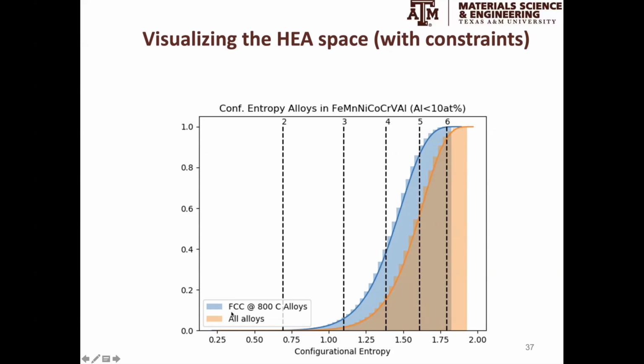When we look at alloys that pass this phase stability constraint, being FCC at 800 Celsius, we see that the actual entropy is displaced to the left. What this means, in this admittedly confusing plot, is that alloys satisfying this constraint have less entropy, or are less complex, than the total potential alloy space. This kind of makes sense: alloys that satisfy a particular constraint are not equally distributed in the entire FCC space we were trying to explore.